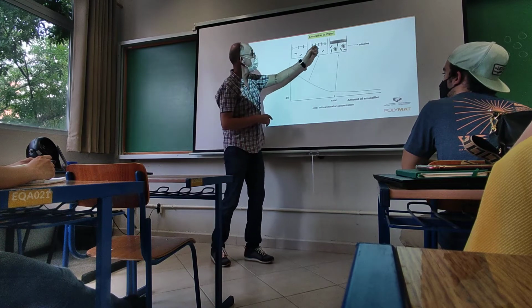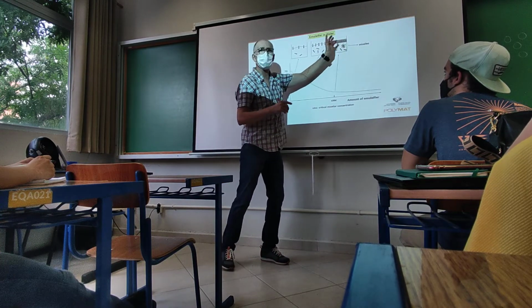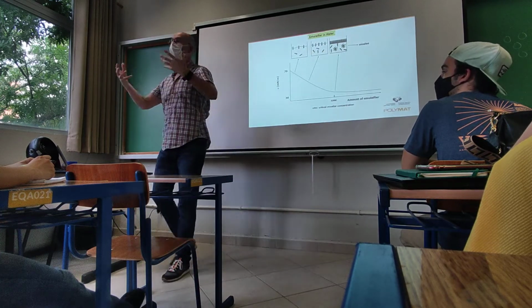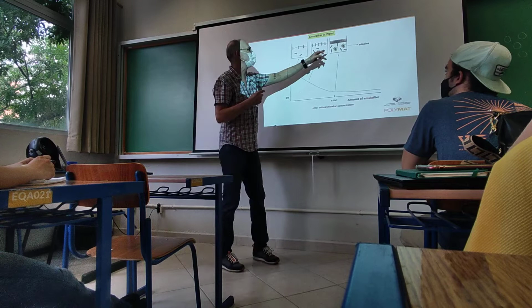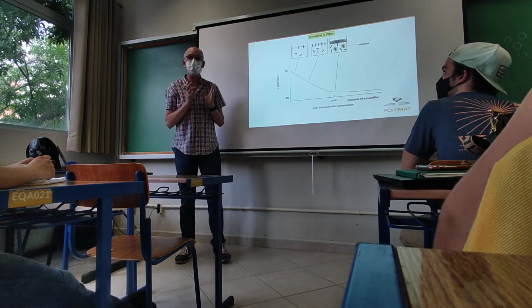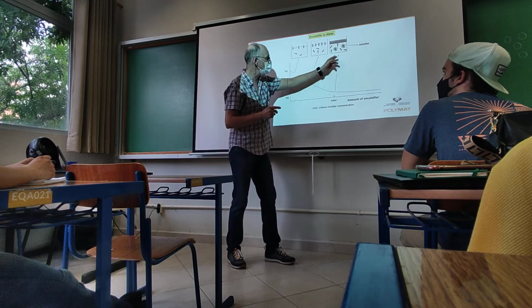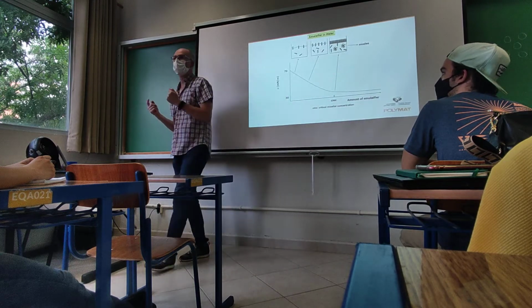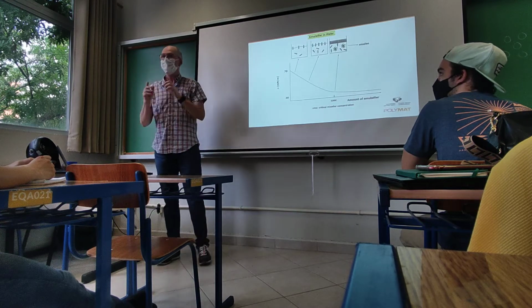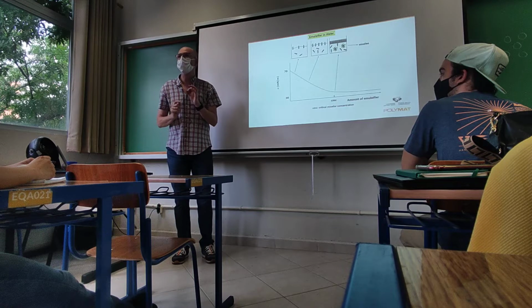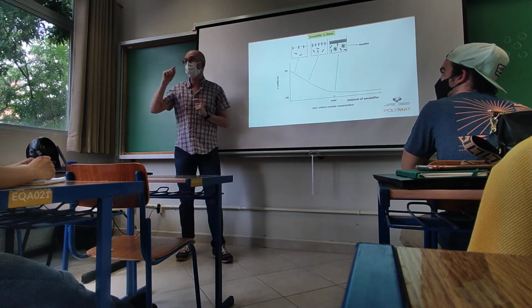Okay? It will reach a point in which all the surface is covered by surfactant, the solubility in water is occupied, and then the surfactants self-aggregate. Surfactant molecules self-aggregate forming micelles. And this occurs at a concentration that is called the critical micellar concentration of the surfactant. And this is a characteristic of the surfactants, the critical micellar concentration or critical aggregation concentration.